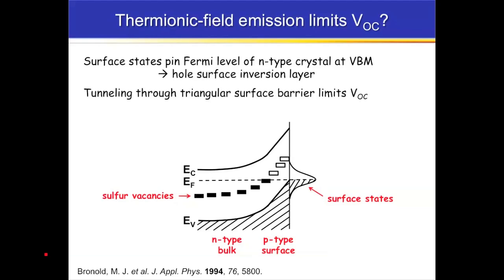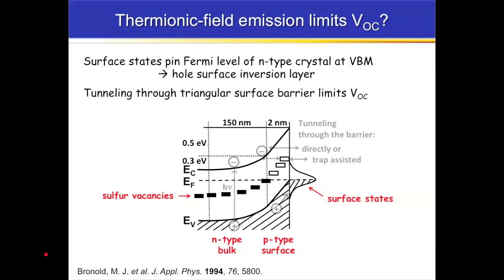And they also believed that they had sulfur vacancies present in the material. And so sulfur vacancies in the bulk are basically not ionized, but near the surface they would be ionized. And this would lead to a very sharp triangular potential barrier right at the surface that might be only a few nanometers thick. And it's a very nice situation for tunneling. And so what they believed is happening here is that most of this built-in potential, most of the band bending, is actually lost because you've got promoted carriers exploring the surface region and basically tunneling right through the top 0.5 eV of the barrier. And this is called thermionic-field emission.